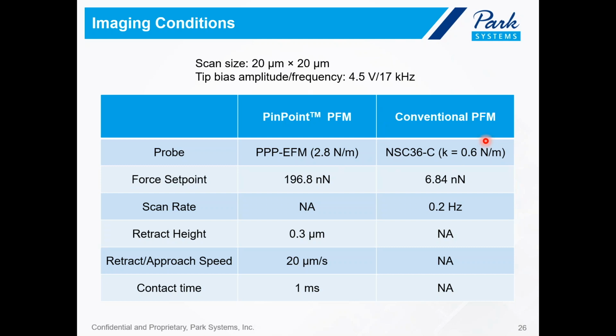And thus, we used a cantilever with a smaller force constant, as you see here, the NSC36C, in hope to alleviate this scratching on the surface problem. Albeit that this NSC36C cantilever has a much smaller force constant compared to the PPP-EFM, the probe was still dragging on the surface and resulted in imaging artifacts in conventional PFM. So I want to show you the image in the next slide, so you can have an idea of what I mean by scratching on the surface.